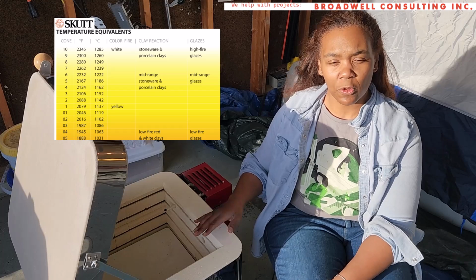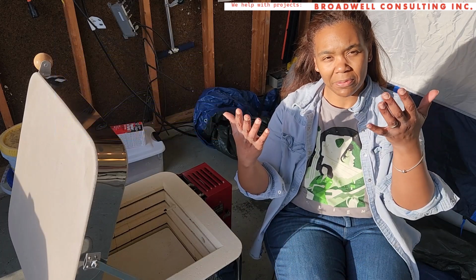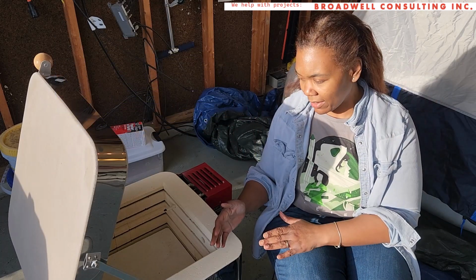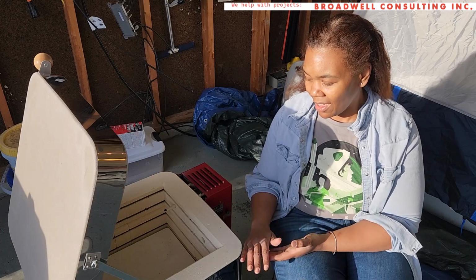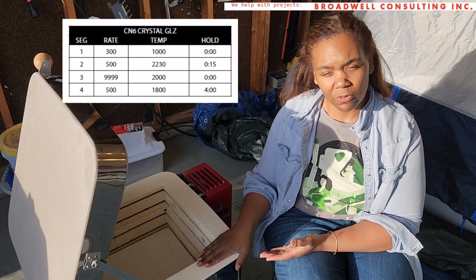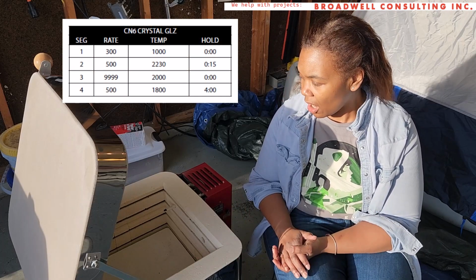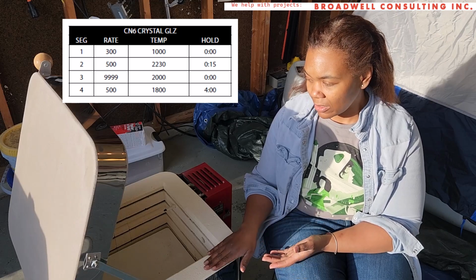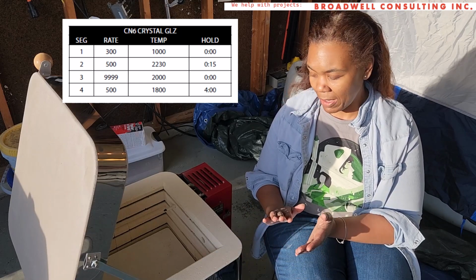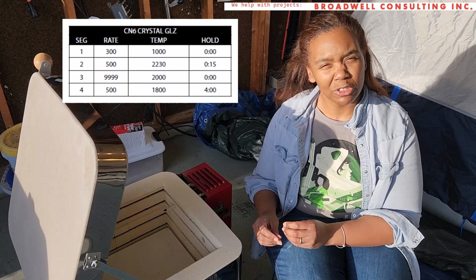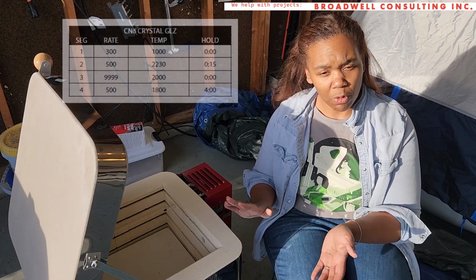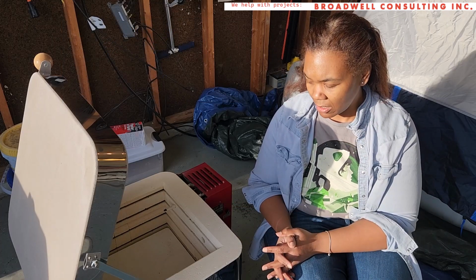It takes about a full day for the kiln to come all the way up to temperature and go all the way back down to where I can open it. I can't open it until it's about 115 degrees. If I do, it could shock the pieces. And I generally, just to be safe, give all of my pieces a preheat to make absolutely sure there's no moisture in it before it starts rising to the firing temperature.